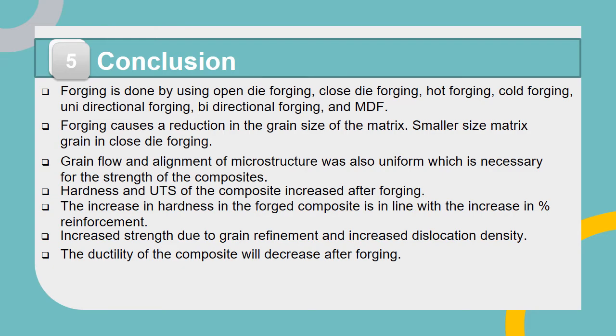Conclusion. The conclusion of this review article is that forging is done by using open die forging, closed die forging, hot forging, cold forging, unidirectional forging, bidirectional forging, and multidirectional forging. Forging causes a reduction in the grain size of the matrix. The matrix grain is smaller in closed die forging. Grain flow and alignment of microstructure were also uniform, which is necessary for the strength of the composite.